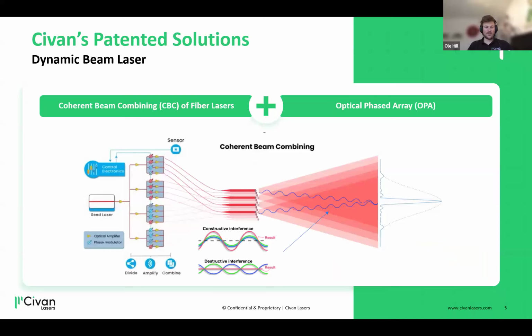So let's get shortly into how we do it with a Civan laser. Maybe you have heard the term "32 lasers in one," and that is kind of true. We start off with a seed laser that is split up into 32 individual channels. Because they all originate from the same seed laser, they are in coherence with each other. Then these 32 channels are pumped up to the desired laser power. For example, in the case of the laser in Hanover, we have up to 12 kilowatts of laser power, so each individual channel is pumped to something like 400 watts. And the phase of these channels can be tuned very precisely and also insanely fast, in the megahertz range.